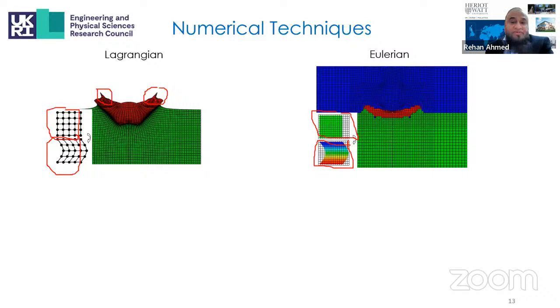The technique can be used to capture large deformations without stability issues or issues related to the aspect ratio of deforming mesh in the Lagrangian analysis. And it is also possible to combine both Lagrangian and Eulerian analysis, for example, where the splat can be modeled as a Eulerian part and the substrate as a Lagrangian in thermal spray coatings.